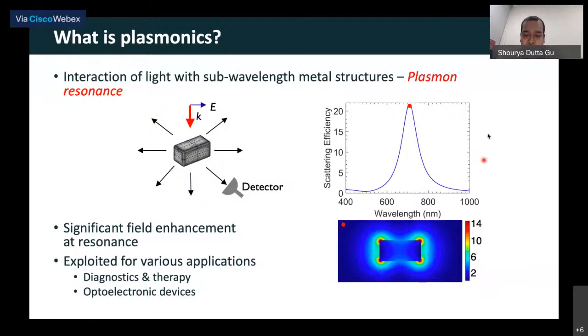The horizontal axis is the wavelength of light that we are sending in, and the y-axis is the scattering efficiency, or the intensity at the detector. At this wavelength of around 700 nanometers, you have a peak. The scattering is, let's say, 20 times higher compared to the non-resonant wavelengths. Now, if you don't put the detector very far away, but come very close to the structure, to what we call the near field, and look at this particular wavelength, you will see a plot like this. The color here, from blue to red, represents the electric field amplitude.